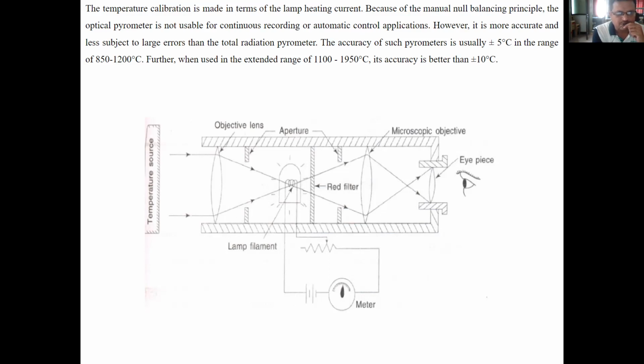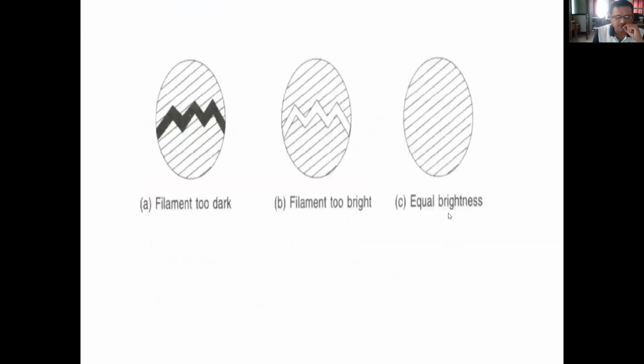for continuous recording or automatic control applications. However, it is more accurate and less subject to large errors than the total radiation pyrometer. The accuracy of such pyrometers is usually plus minus 5 degrees Celsius in the range of 850 to 1200 degrees Celsius. Further, when used in the extended range of 1100 to 1950 degrees Celsius, its accuracy is better than plus minus 10 degrees Celsius. Therefore, this is the selective radiation pyrometer.